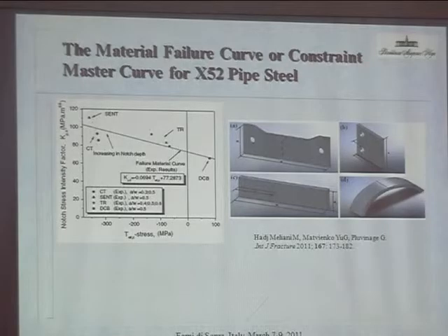Yes. And even if you would plot the fracture toughness, the specimen thickness would not fulfill the ASTM requirement, or? No, we will have a similar effect. Okay, I'm sure. But here we have the same thickness for all specimens. Do you think that you will also have such a T-stress effect if you would fulfill the thickness as well as the ligament criteria? Yeah, but in this case we need to incorporate in this picture and basic equations the T33 stress corresponding to out-of-plane constraint. It will change with thickness. Yes, exactly.